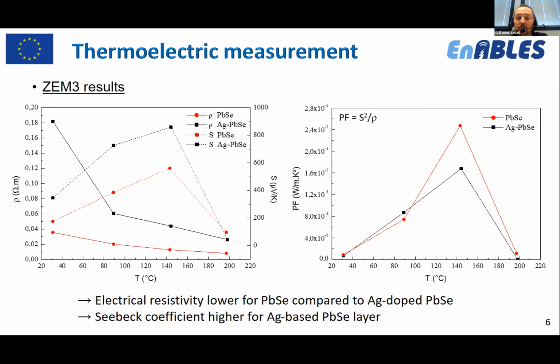And on your right, you have the temperature dependence of the power factor. The power factor is defined here by the square of the Seebeck coefficient divided by the electrical resistivity. It indicates partially if a thermoelectric material is good or not. And so here you have the comparison between both samples. First, as you can see, we obtain a peak around 140 degrees C. But except for this peak, you can see that we don't have any influence of silver doping